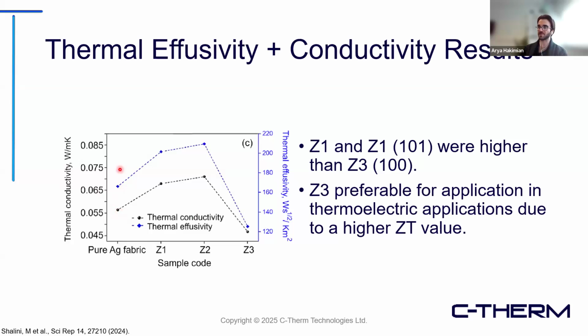So interestingly, when they started with just their pure fabric here, I'll just use this line as the example, we're sitting a little bit above 55 milliwatts or so, right? Through the introduction and when they were forming... Oh, that's the typo. That should be Z2, sorry. So the Z1 and Z2 formed a crystal structure in the 101 direction, and they were higher. They ended up boosting that performance compared to the Z3, which was the 100 direction. And as we can see, these two actually went the opposite route that they were looking for. But then the third variant there did actually show a performance increase, because the conductivity and effusivity decreased for this specific application.